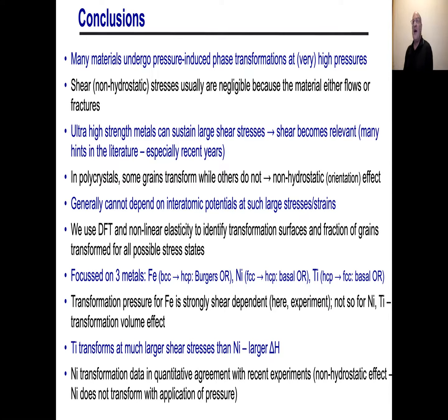And I think we should be able to do it, just like we know that there's an activation volume for things. Depending on how you want to say this, there's an activation strain tensor, right? And that activation strain tensor certainly does have shear components, because the transition paths tend to be shear paths. Now, if you go to cases where the transformation has a diffusional component, then I have to ask about the effect of shear on the diffusion constant tensor. It's an interesting question. I would imagine somebody's looked at it. I haven't, but maybe Lindsay.